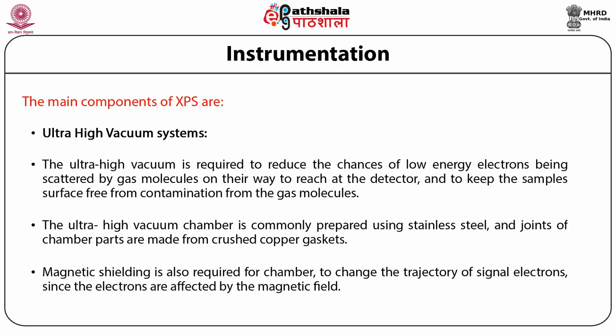The ultra high vacuum chamber is commonly prepared using stainless steel, and joints of chamber parts are made from crushed copper gaskets. Ultra high vacuum can be achieved using diffusion pumps, sputter ion pumps, or turbomolecular pumps. Magnetic shielding is also required for the chamber, since the electrons are affected by the magnetic field, which changes the trajectory of signal electrons. Second is the source guns. It contains X-ray guns, electron guns, and ion gun.